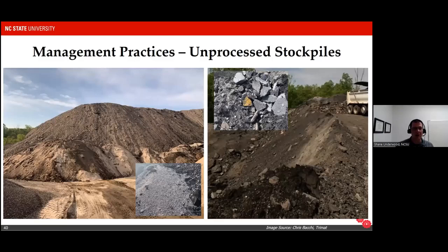So here is one contractor who has a RAP stockpile. This RAP stockpile is very dark brown, but not black in color. And they're actually stockpiling some sand and fine particles at the toe of this stockpile. So when they take from this, they actually pick up RAP, but they pick up some extra sand as well. You can also see on the image on the right, again, we have this large stockpile that we're dumping on. Here we have both millings and we've got these broken slabs of asphalt that get incorporated. And all of those differences are going to get processed into the final RAP stockpile that's used.